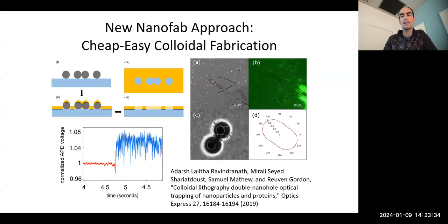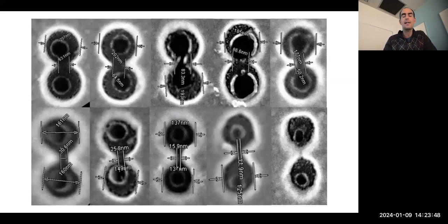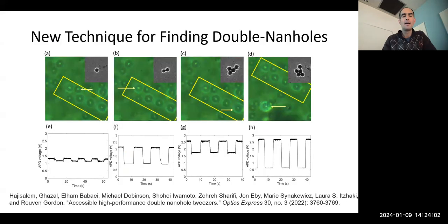We make these apertures by a bottom-up approach. We use polystyrene spheres, drop them on a surface, evaporate gold over them, and then do sonication to remove the polystyrene spheres. We can also do plasma etching to precisely control the gap down to 10 nanometers, in very small increments, giving very fine control of the gap between the cusps of the double nanohole.